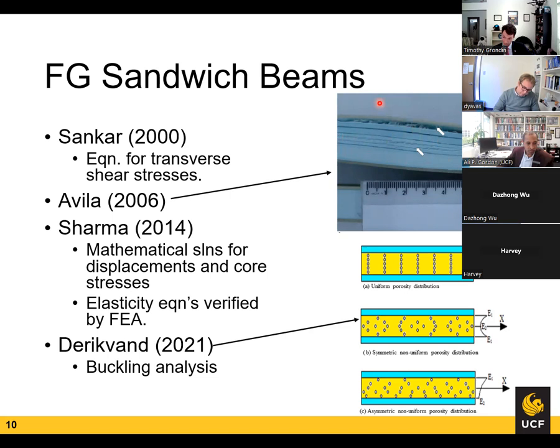On all of these, they were asymmetric, going linear from low density to high density or high density to low density. And it was found that there was no significant bending stiffness increase in the asymmetric core materials. The highest performer, however, was putting the highest density foam at the top, and this increased the wrinkling stress that it could take in the upper surface, as well as decreased core plastic collapse.